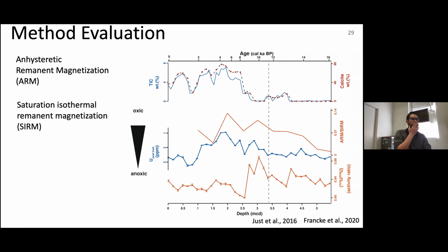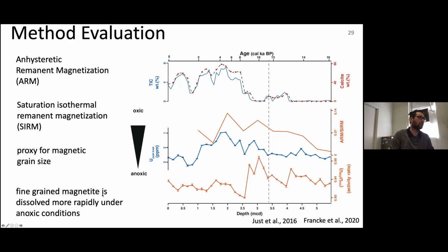Then the final thing I want to talk about in terms of geochemistry, just two more slides on that, is the redox conditions, basically before and after deposition. So after deposition, because there was a lot of previous work done on Lake Ohrid, a lot of rock magnetic analysis, for example, here by my colleague Jana Just, we actually had quite a few proxies that we can use to understand the redox conditions in the sediments, just before and after deposition at the DEEP site. And we used in that case the ARM-SIRM ratio, which is a proxy for magnetic grain size. And not going too much into details, but fine-grained magnetite is dissolved more rapidly under anoxic conditions, which is picked up by this proxy.